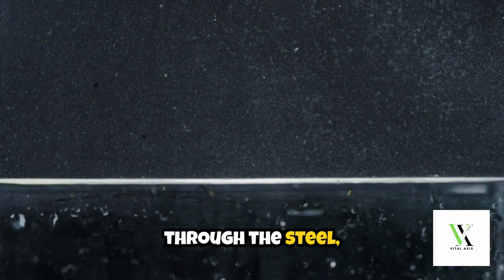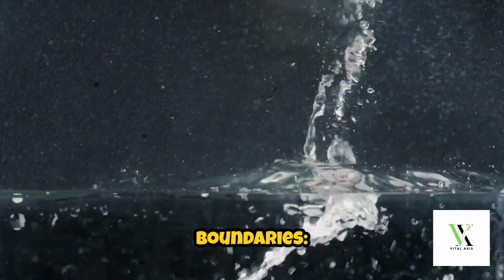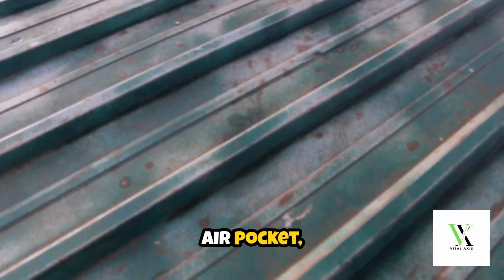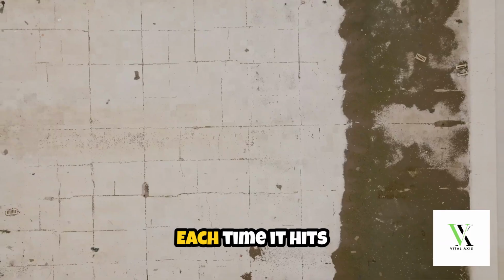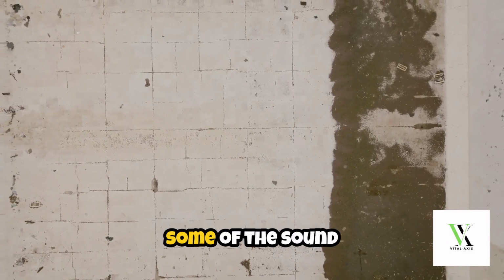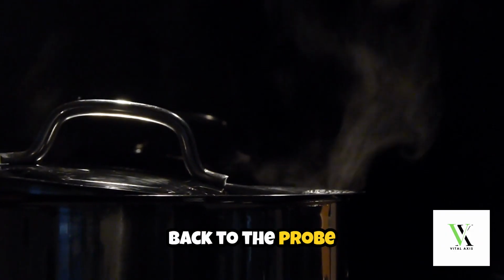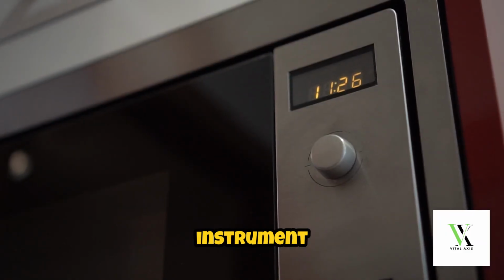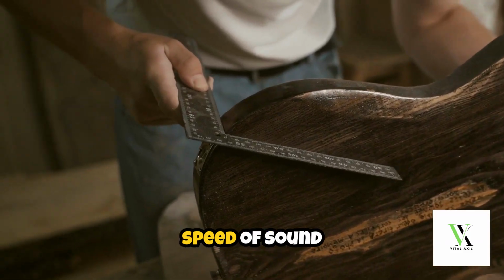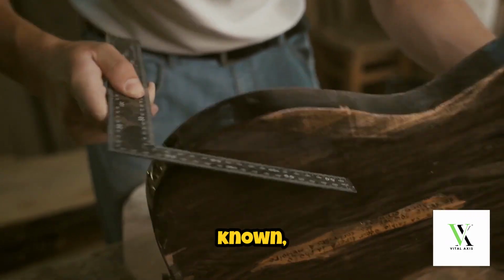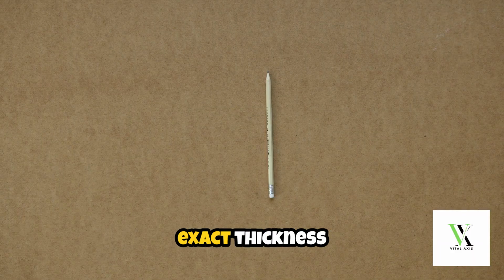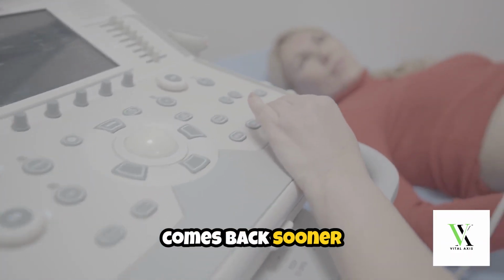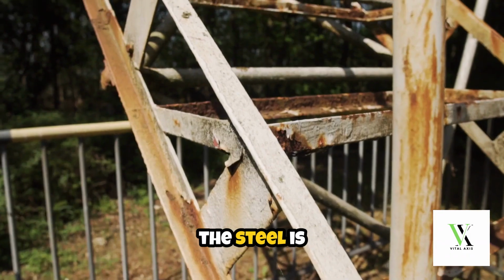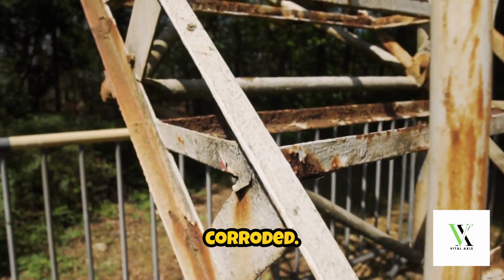As it passes through the steel, it encounters boundaries: the back wall, a possible air pocket, a patch of rust. Each time it hits a boundary, some of the sound is reflected back to the probe as an echo. The ultrasonic instrument measures the time it takes for the echo to return. Because the speed of sound in steel is precisely known, the time delay tells you the exact thickness of the steel at that point. If the echo comes back sooner than expected, it means the steel is thinner, perhaps corroded.